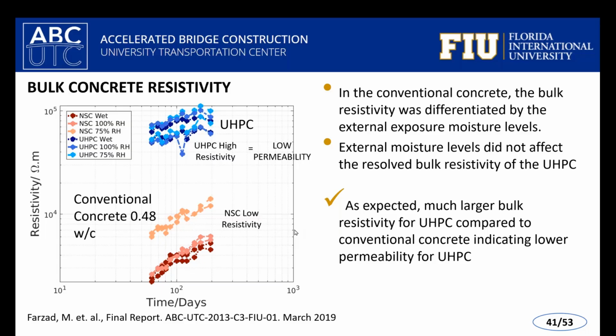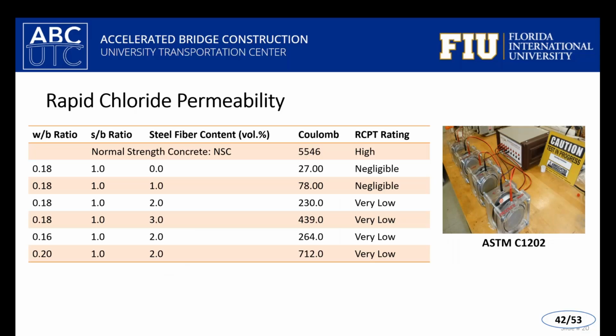But in the case of UHPC, whether we kept it in ambient condition at 75% humidity or we soaked them, there wasn't really an effect, because UHPC is such a dense material. So the moisture never really had opportunity to enter into the concrete pore network. So even with very wet environments, it still retained very high resistance and resistivity. Beneficial again because it prolongs the time it takes for any aggressive ions to move. It causes a less effective coupling of a system, and also is probably related to possible gas movement in the system as well. I'll mention some of my colleagues at FIU who helped with some of this work.